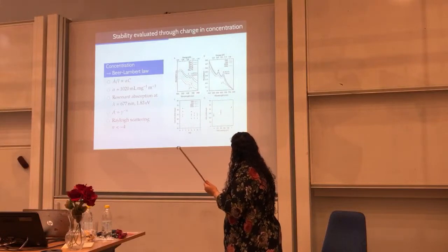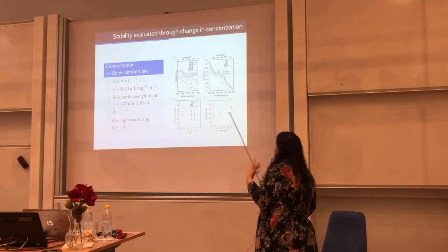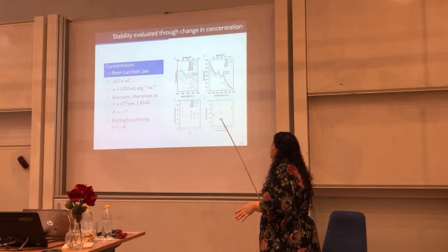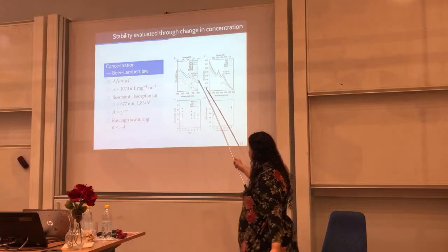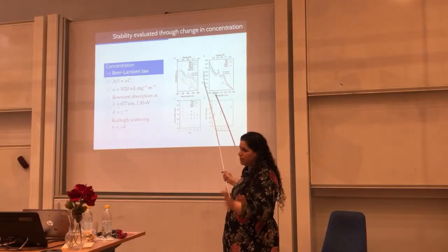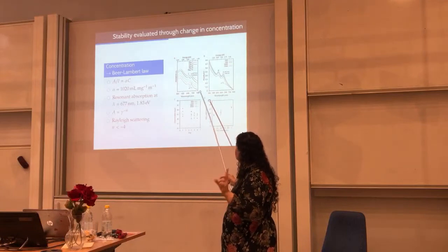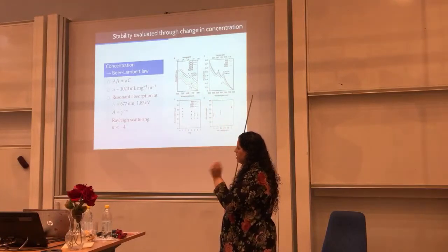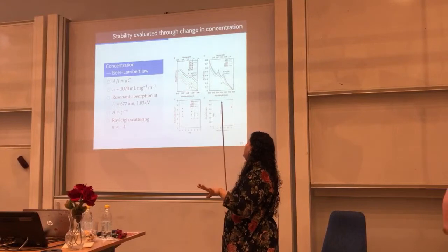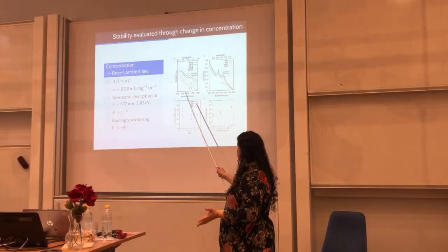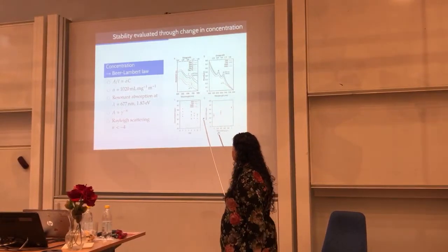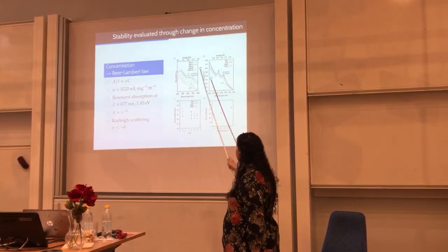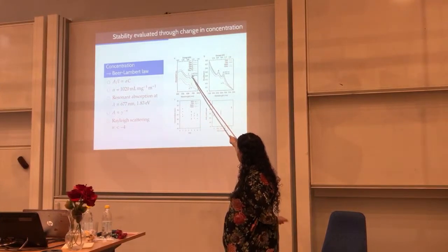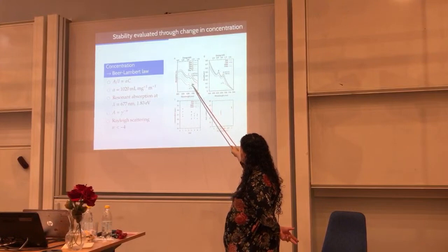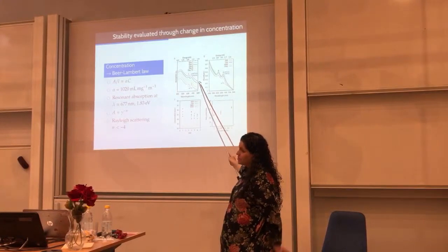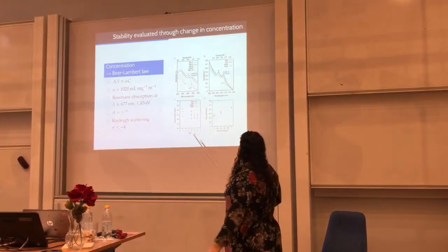Okay, so I'm interested in the shelf life of the material, right? So then I measure this over time, daily, at the same time, the same dispersion that was very well sealed, so then to avoid the evaporation, so I can evaluate how the concentration is changing. So if I take the red curve here, this would be day one, and then of course the concentration is dropping. So it means the particles are sedimenting.